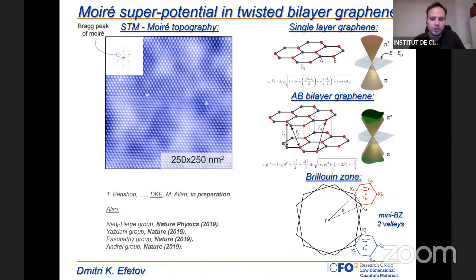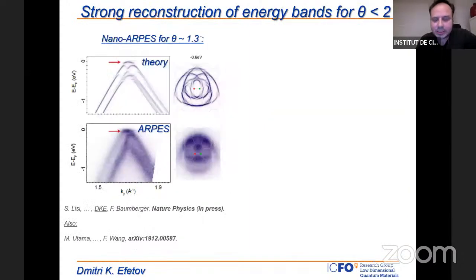really image these. This is a typical scanning tunneling microscopy measurement of some of our devices, which were performed in Milan Allen's group in Leiden, and they really can image those periodic moiré superpotentials, and we can find that these are quite periodic, stacked along the device. And these periodic structures which you see here are not individual atoms, but the individual moiré lattice sites.